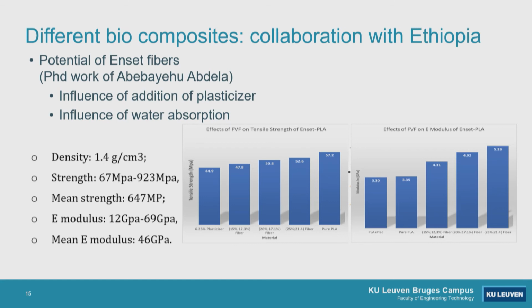Another material that has been used is this Enset fiber. This is a kind of banana leaf fiber, and there also the amount of fibers has been changed, and you see a nice increase. Well, not an increase. On the right side, you have the pure PLA. On the left side, we added 6% of plasticizer. You, of course, see a decrease there, but then adding the fibers again, you see a possibility to tune the properties. Looking at the modulus, you can also see a serious increase when adding the fibers for this Enset fiber.